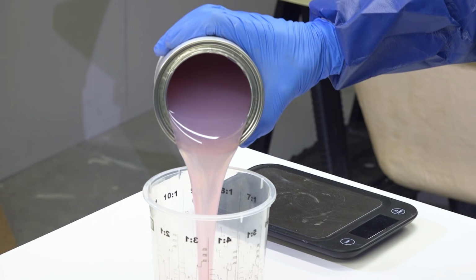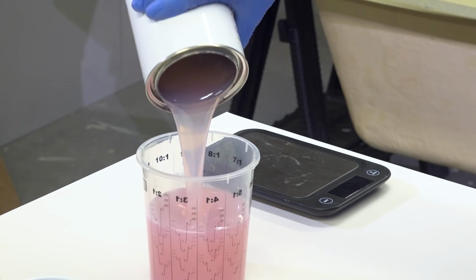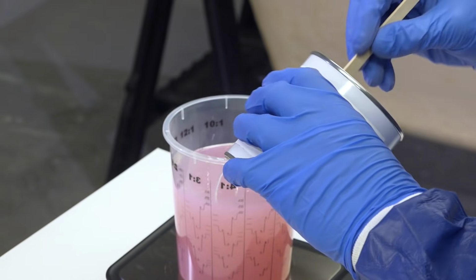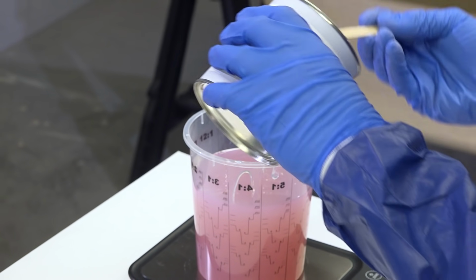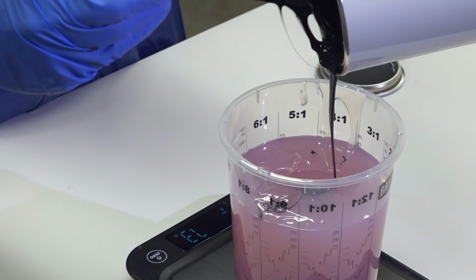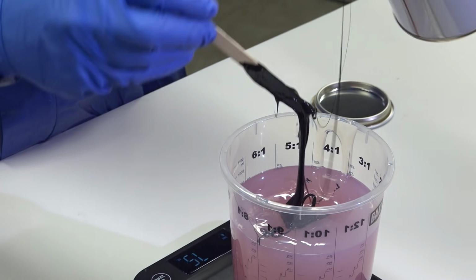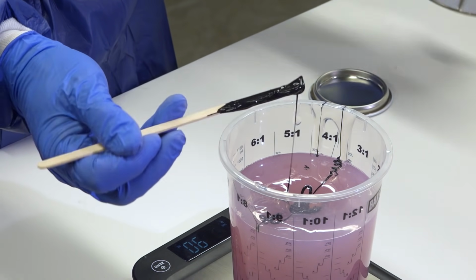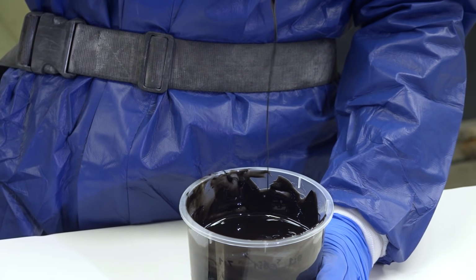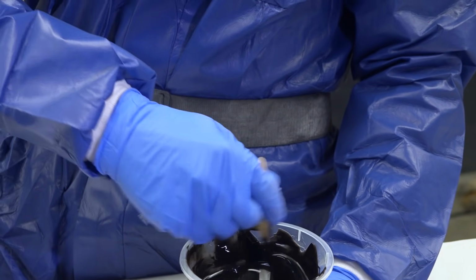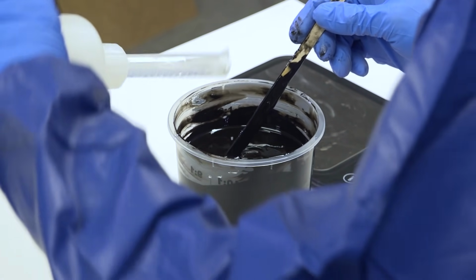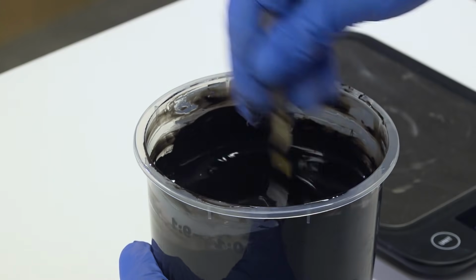This is specifically designed for use with an epoxy backing resin. Normal polyester gel coats can only be used if you're using a polyester or vinyl ester resin for the main infusion. The GC50 can be used clear, but in this case we want the part to be black, so a polyester pigment is added to the gel coat at 5%. As this gel coat is polyester based, it then needs catalysing with the MEKP catalyst at 2%.